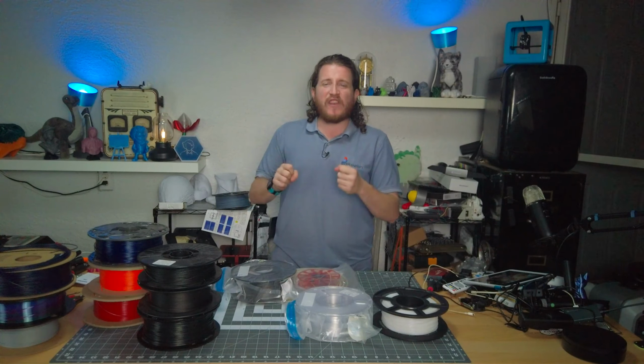But be careful, especially with the carbon fiber and glass fiber filled. 0.4 millimeter nozzles are just asking for problems. Go with a 0.6 or above to keep the clogs at bay. Especially the quality stuff, this 3DX Tech material, the strands of carbon fiber are often long enough and large enough to clog up a 0.4 millimeter nozzle. Ask me how I know. But at a 0.6 or above, you should be running it just fine.